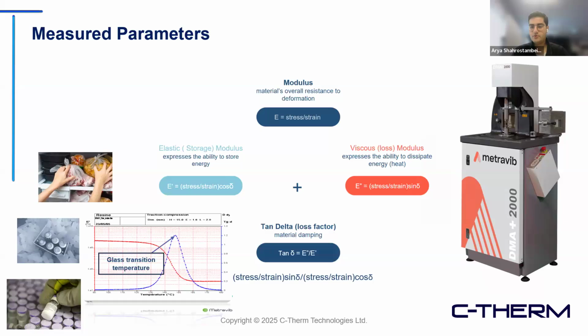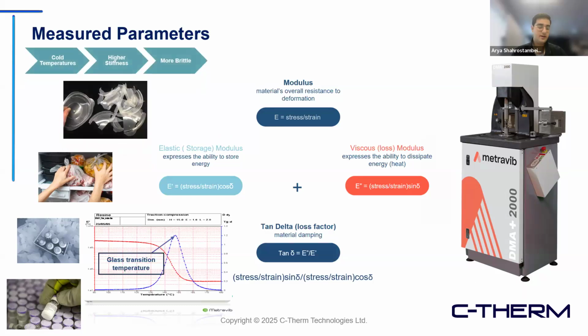An important point to know is that testing samples at lower temperatures, especially viscoelastic materials, requires high force capability. Since the material goes lower in temperatures, it becomes stiffer, and more mechanical force is needed in order to deform the material and have an accurate measurement of viscoelastic properties. So in other words, the colder the temperature, the higher the stiffness, and the more brittle the material.